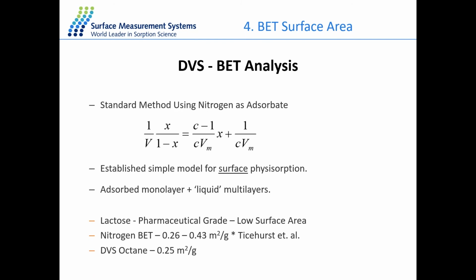So normally the water sorption or moisture sorption is not very recommended to calculate the BET surface area, because the water isotherm is usually a type 3 isotherm, which means there are more water-water interactions. The water is forming clusters on the surface rather than covering the whole surface with a monolayer.